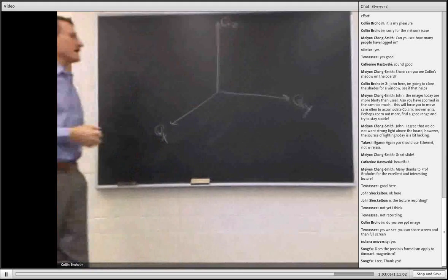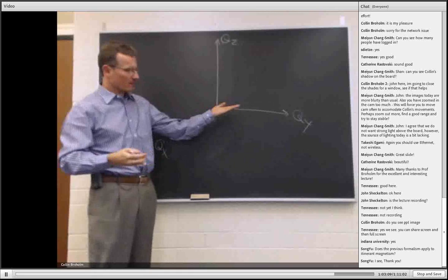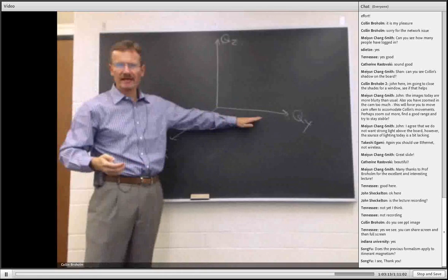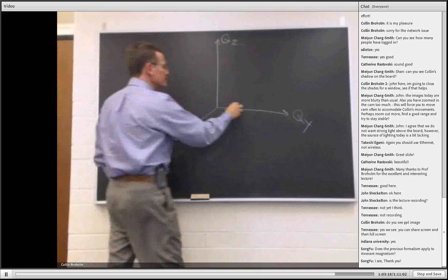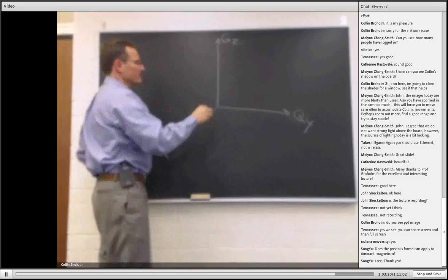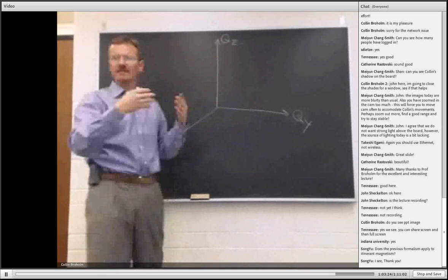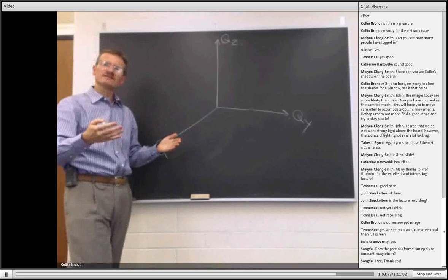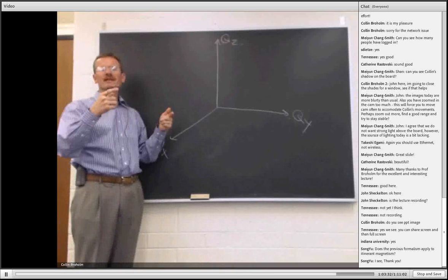And imagine that I have these planes of my two-dimensional magnets forming the Qx, Qy plane. Now, because there are no correlations in the z direction, there'll be no interference effects in the z direction. And so the entire diffraction cross-section will not depend on the z component of momentum transfer.